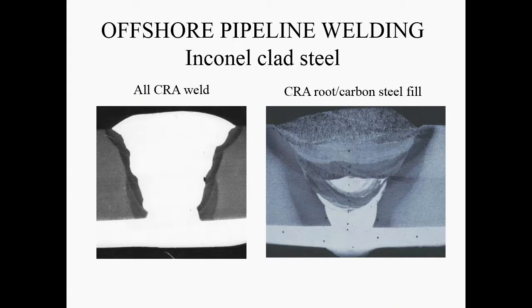Because we're looking at two things. One is that we want to produce a sound weld, and the other one, we don't want to increase the cost dramatically. So in the first case, the weld was made using a consumable made from the same material as the clad, so from Inconel, remember, which is very expensive. And in the second case, well, you can actually say from here that it's very obvious that we've used different materials for the consumable. So that's the root bit. What consumable do you think we've used here? Inconel, yeah, because you see it's exactly like here.